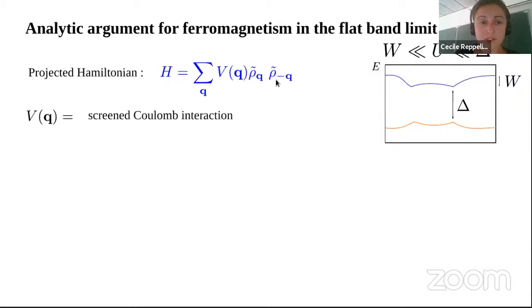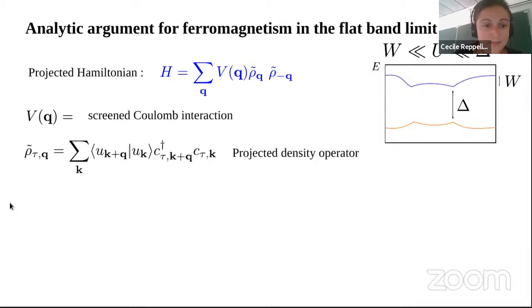So here I've written down the projected Hamiltonian. We're doing a projection onto a Chern band, so it's much easier to do it in momentum space. So V of Q is your favorite interaction, and typically you would use a Coulomb interaction, and maybe you can take into account the effect of screening in it. But here this is very generic as long as it is a repulsive interaction. Then rho Q with a little tilde. The little tilde means that we have done the projection onto the conduction band.